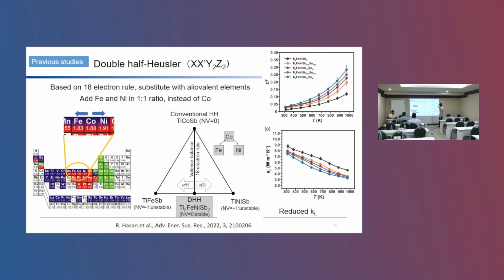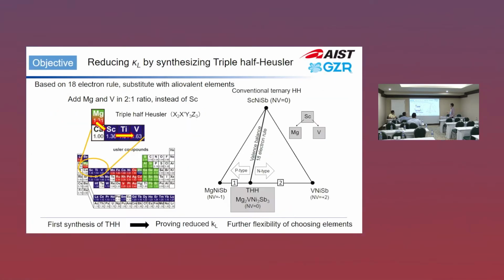And ZT is still not that high, but the lattice thermal conductivity is quite low compared to the parent ternary phase or general Half-Heusler structures. So it works. People are still trying to improve the performance, but the idea itself is kind of interesting. So I tried to expand this to a triple Half-Heusler.